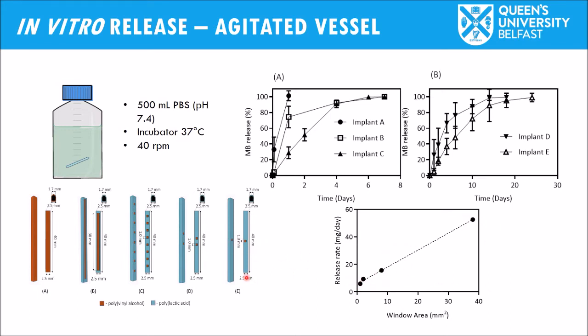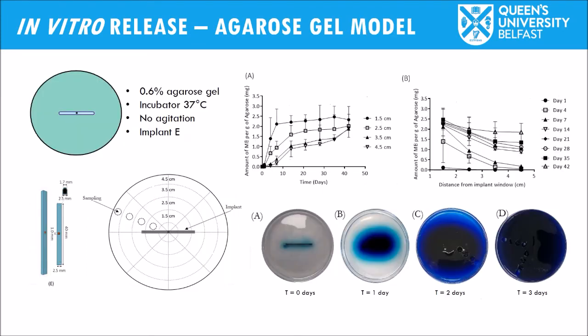The release window. This was really promising, considering that methylene blue is a highly soluble compound. We can get up to almost a month of release, 25 days. Still, for certain applications this will not be great, but at least by tweaking the design of the implant, we can affect the drug release rate. We believe that the testing method that gave us 25 days of release is not the most representative, because the implants were placed in PBS, phosphate buffered saline, and those are not representative conditions of the in vivo situation.